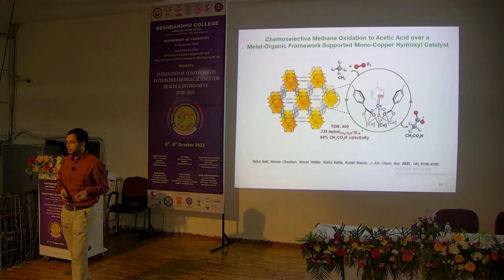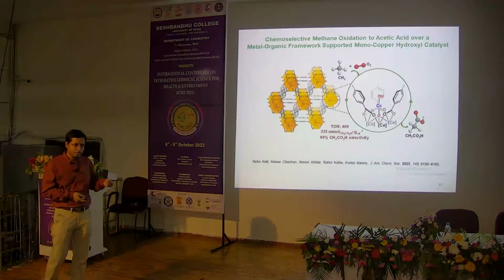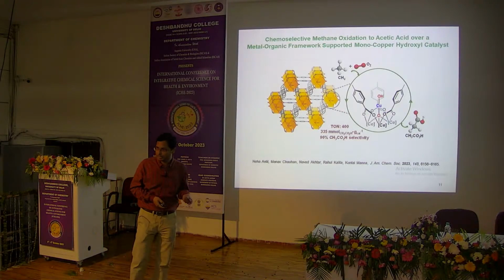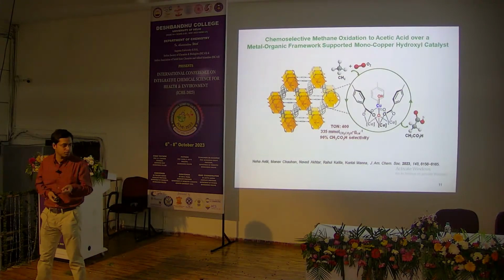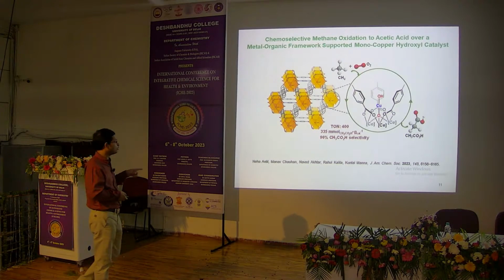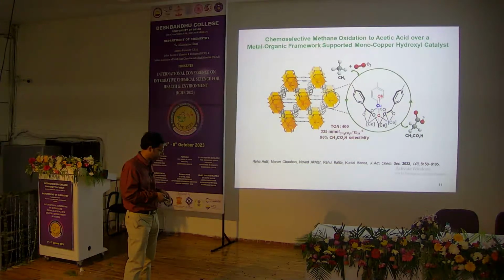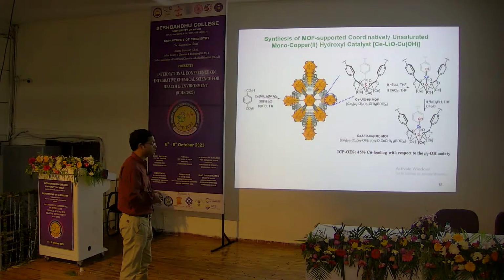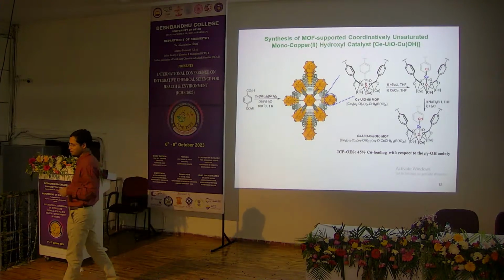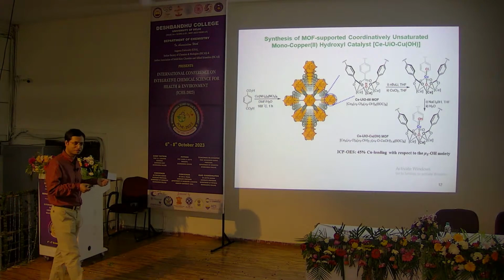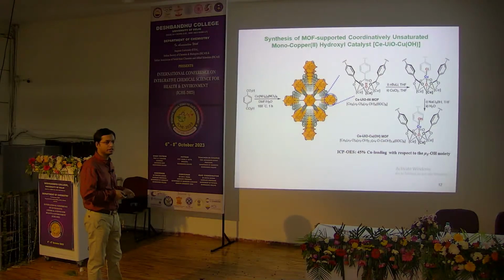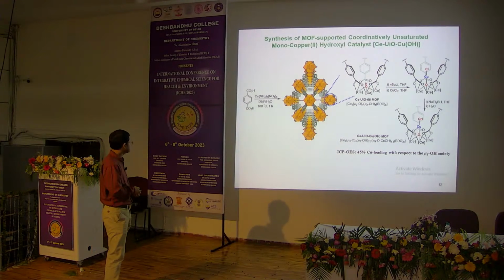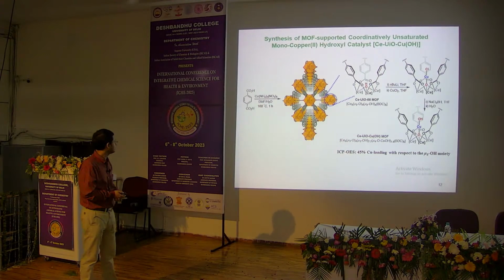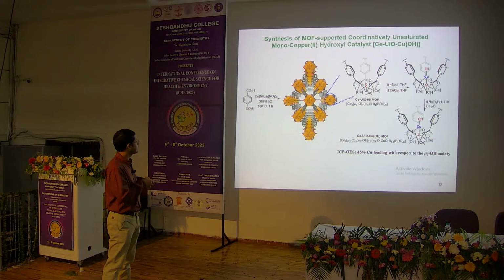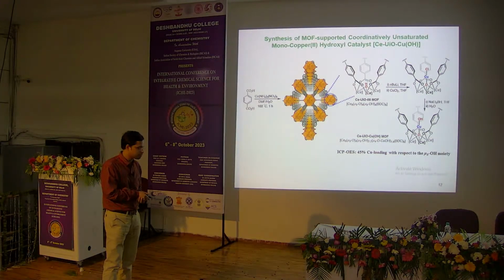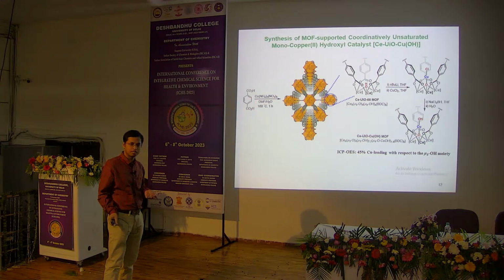So now I am going to talk about the development of a single site copper hydroxyl catalyst using a UiO type MOF, which can directly convert methane to acetic acid using oxygen as the oxidant. The catalyst synthesis is very simple. It's very straightforward. Basically, if you just heat, by solvothermal synthesis, ceric ammonium nitrate and benzene dicarboxylic acid in DMF at 100 degrees centigrade, within 1 hour you will get a very crystalline UiO type MOF using cerium SBUs.